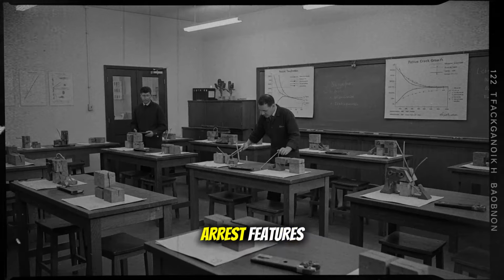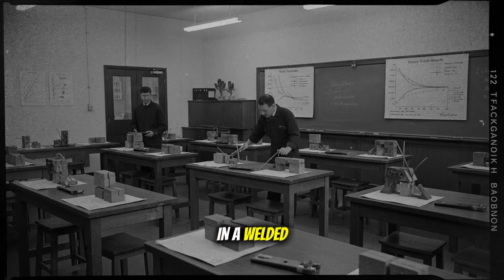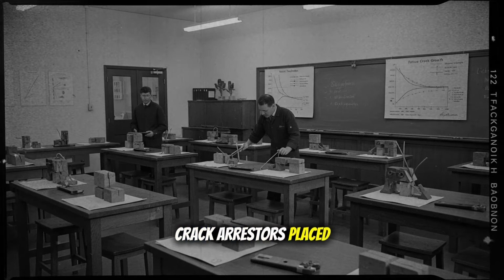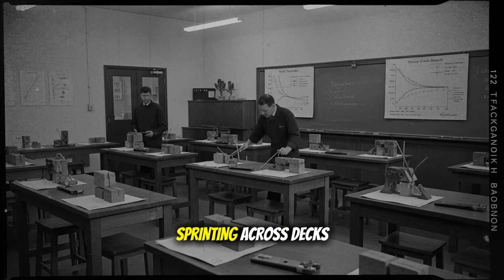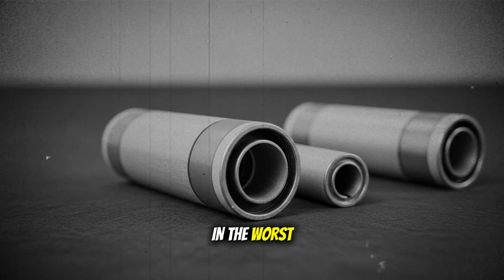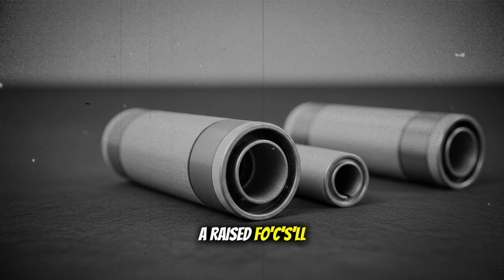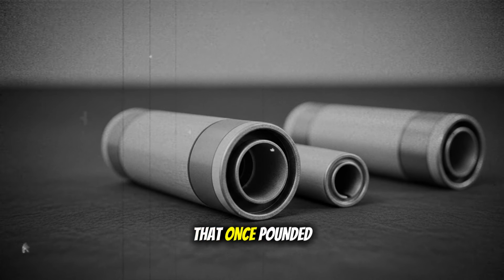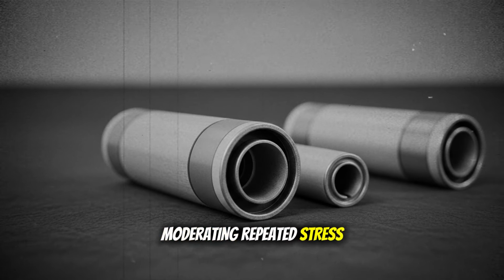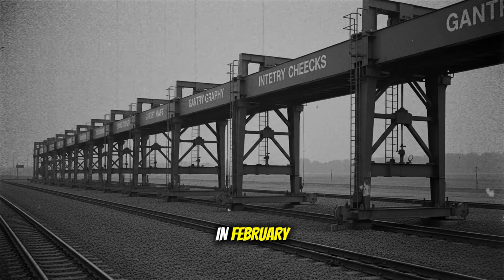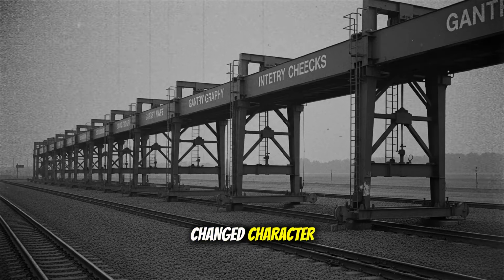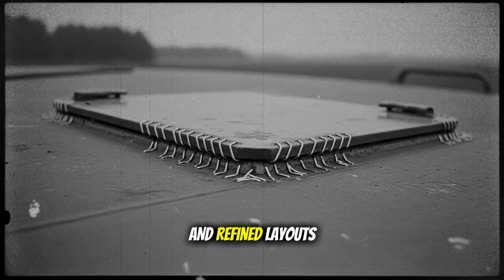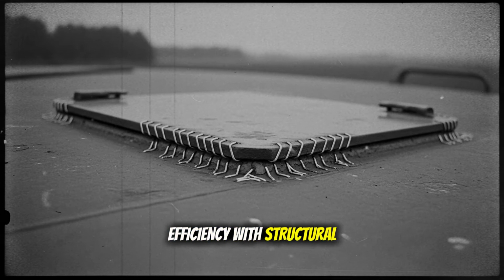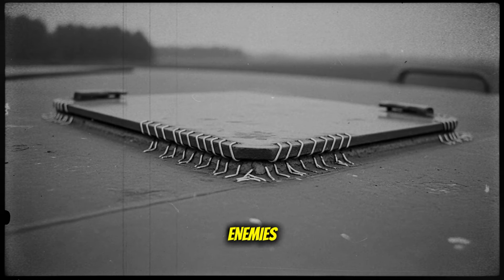Designers also embedded arrest features and details that acted like speed bumps in a welded world, with angle iron crack arresters placed at vital locations to prevent a local flaw from sprinting across decks and side shells as it had in the worst Liberty casualties. A raised forecastle improved seaworthiness by shedding green water that once pounded the well deck, moderating repeated stress cycles that add up over weeks into the kind of cumulative fatigue a brittle plate cannot forgive in February. Even cargo handling changed character, 7 sets of cargo gear across 5 hatches, electrically powered winches, and refined layouts that balanced service efficiency with structural continuity rather than treating those priorities as enemies.